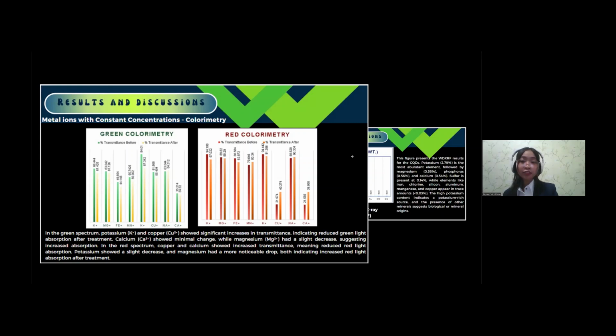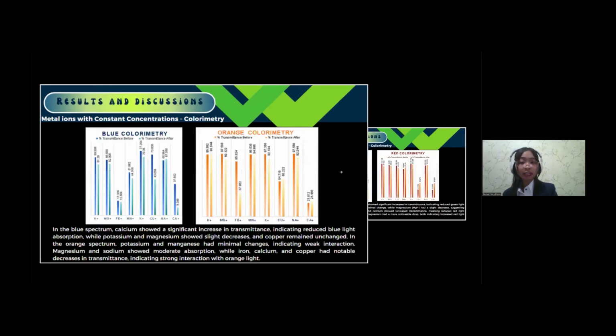The second figure shows the effect on red light. Potassium slightly absorbs more red light after treatment, but copper and calcium both let much more red light through, so they absorb less. Magnesium, on the other hand, absorbs more red light after the treatment. Next, the first figure shows how the CQDs affect blue light. Potassium absorbs a bit more blue light after treatment, copper stays the same, calcium absorbs much less blue light, and magnesium absorbs slightly more blue light.